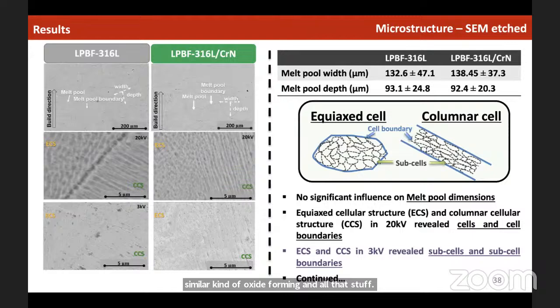microstructure, the cross-sectional microstructure, and side by side you have one material printed with 316L, another 316L with chromium nitride. Looking at the melt pools and all that stuff, we see pretty similar microstructure. The difference we start seeing is when we go to really careful, high resolution SEM characterization. What we start seeing is that there are some subcells present: you have the cellular structure, and inside the cells you have subcells, and the subcells are pretty refined if I put in chromium nitride.